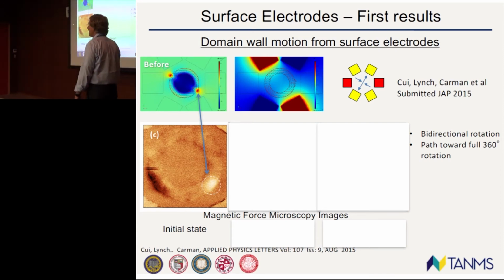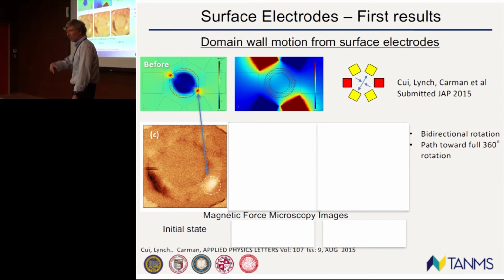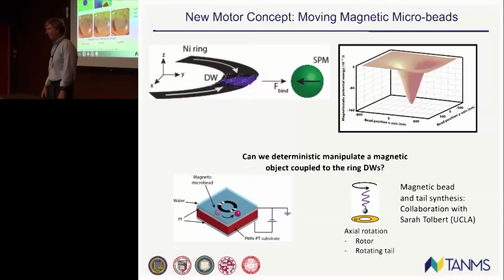And you say, well, have you actually tried to test it out? So this is a ring, thin film PZT, MFM image, that's our north pole. We're going to apply an electric field on these two. We're going to rotate that over 45 degrees. And then we're going to apply another electric field on these two and actually rotate it back 45 degrees. So we can get going back and forth, plus and minus 45 degrees. But once again, that's only manipulating magnetic states. Really, I said you want to actually manipulate mechanical states.